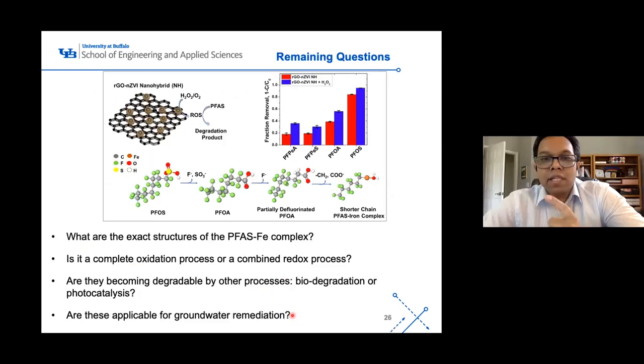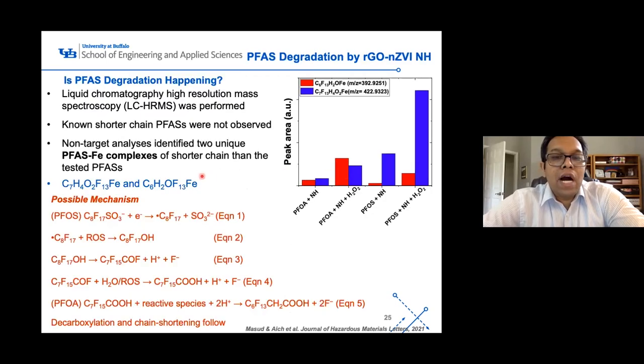I think in the next one. So basically in the first step, from PFOS we get the sulfate and one fluorine coming out, then it all becomes PFOA, and the PFOA releases fluorine first, and then they also release two carbons, one methylene group and one carboxyl group. But at the same time, they are actually attaching the iron on the structure. So that's what we have found.